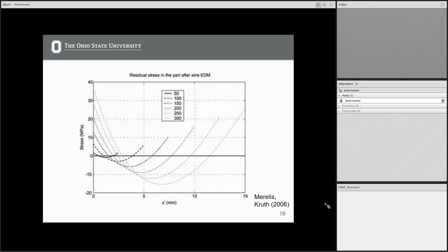So then taking a look at the residual stress after we remove these parts, you can see we get a really big decrease in the maximum stress of the part as we decrease the amount of layers that we're actually printing. However, we still see those same trends where we have tensile portions, compressive portions, and our maximum being towards the base of the part itself.